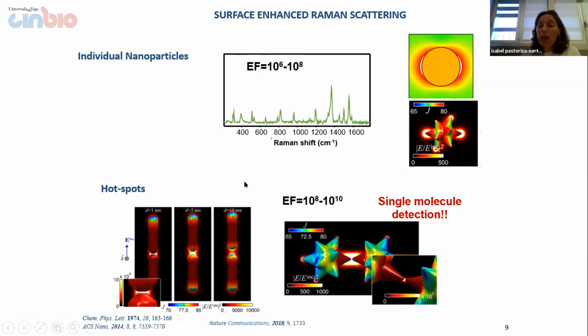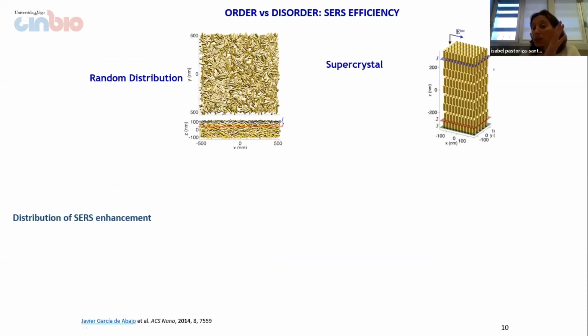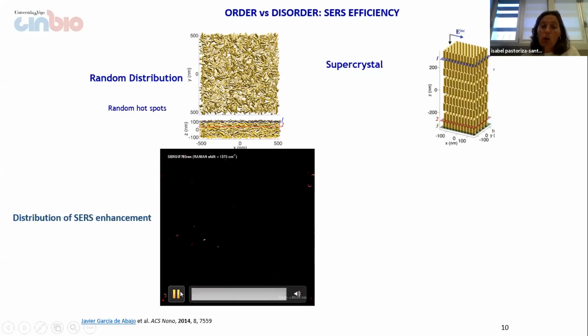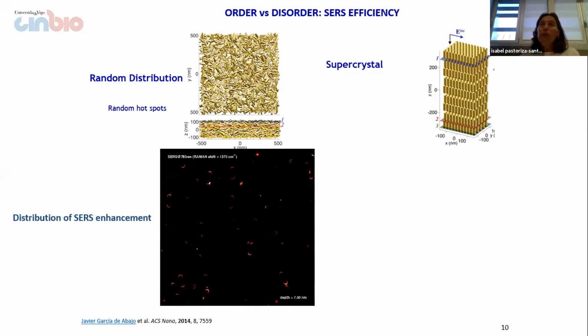But the point is that if we think of an assembly, the nanoparticles can be randomly distributed or well ordered. And Javier Garcia de Abajo and Luis Liz-Marzán some years ago studied both situations and observed that the behavior in terms of SERS enhancement was completely different. So they simulated an assembly of randomly distributed gold nanorods, and in this case, this is a video of the SERS enhancement, what they observe is that when we move from the surface of the self-assembly deeper inside of the assembly, the intensity of the hot spots, meaning the intensity of the SERS signal, decreases till completely decayed.